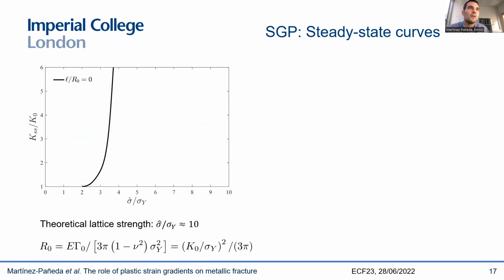So first, I'm plotting the result for conventional plasticity. This agrees with this result by Tvergaard and Hutchinson. You can see that our steady state fracture toughness basically asymptotically increases as you approach 4 times the yield stress, because these are the maximum stresses that you get with conventional plasticity. So there's no chance that you will be able to predict fracture using conventional plasticity models if you have a cleavage strength, a grain boundary strength, that is 10 times the yield stress.